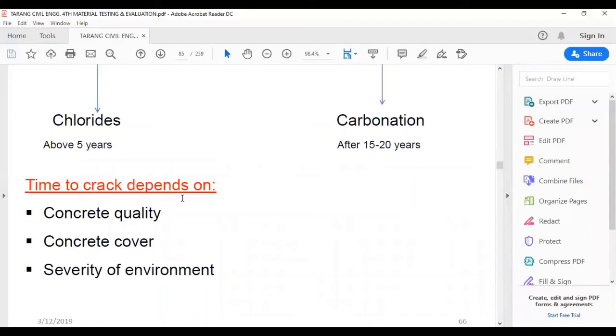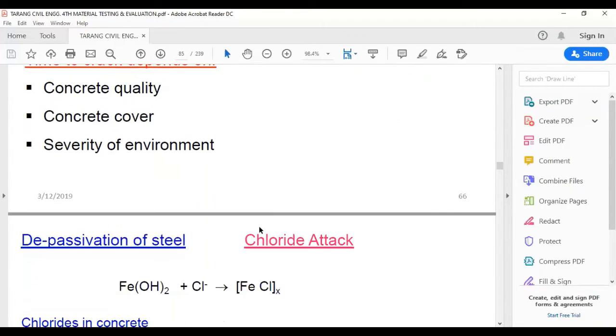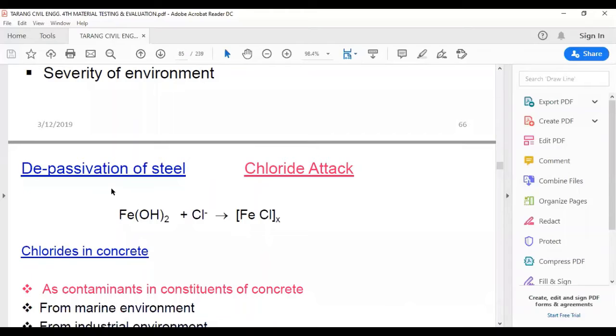So time to crack depends on concrete quality, concrete cover, and severity of environment. Now, the removal of passive layer, that is depassivation of steel by chloride attack. When iron hydroxide forms and it comes in contact with chloride ion, then it forms this FeClx.